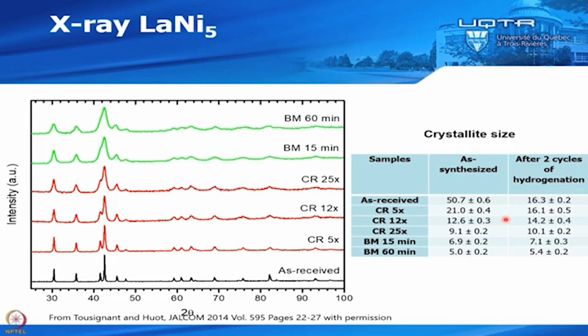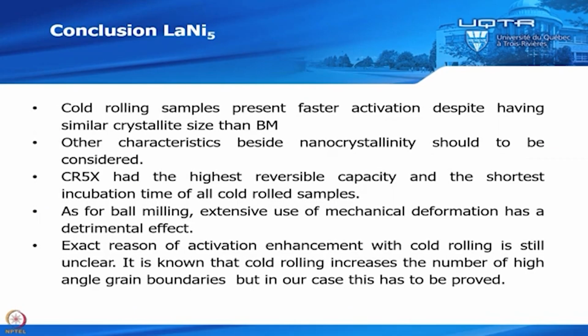Okay, so the conclusion for the lanthanum nickel 5 is that cold rolled samples present a faster activation despite having similar crystallite size to ball milling. So the point that I want to give you here is that nanocrystalline is important for kinetics and for activation, but it's not the only parameter. Some other characteristics also have an effect on the hydrogenation kinetics.